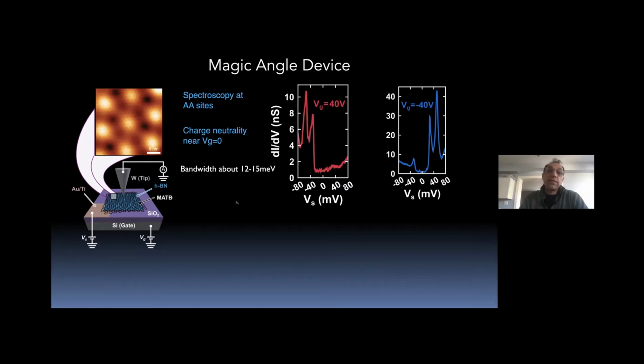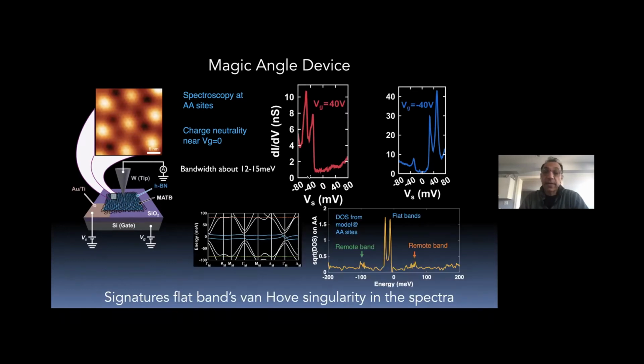The sharpness of these peaks tells you about the flatness of the band, which is about 12 or 13 millivolts in this system. Okay, so these are the Van Hove singularities. In fact, if you take the STM images, you can even take into account the strain that you see in the STM image and input it into a theoretical calculation to understand the detailed shape of these spectra. So the single particle physics of this problem can be beautifully understood with the local STM measurement and using the single particle machinery.